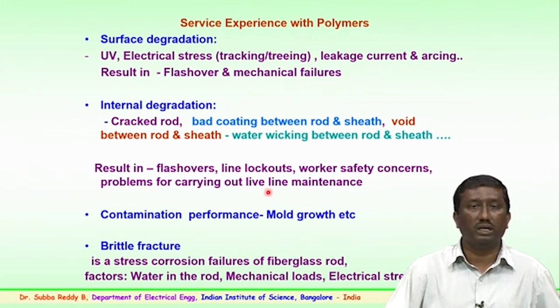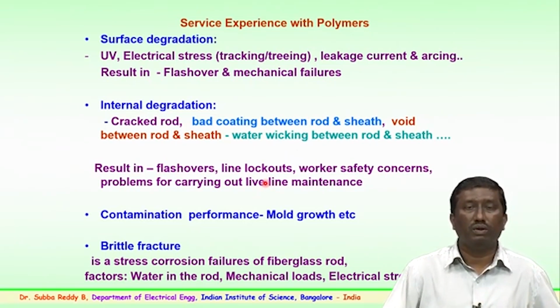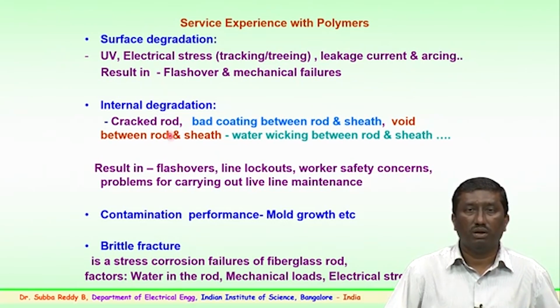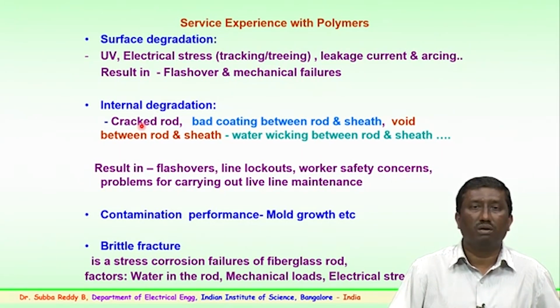Then internal degradation. We know that internally a fiberglass rod is used, where sometimes the hydraulic pressure used to crimp the end fittings, the metal fittings, to the rod could lead to a cracked rod, or sometimes a bad coating between the rod and the sheath. There is a coating which is applied. This could lead to very small voids between the rod and sheath.